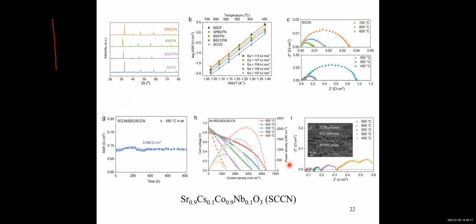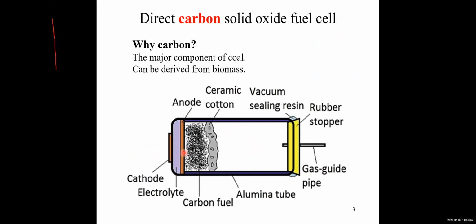It's very good. Then we use this material in SOFC and test the fuel cell performance, and we achieved a very good fuel cell performance. At a temperature of only about 650 degrees Celsius, we achieved a peak power density of around 2,000 milliwatt per centimeter squared, and it's quite stable over 800-hour operation. So this material should be very promising for use as SOFC cathode. That's a very brief sharing about the new material development.